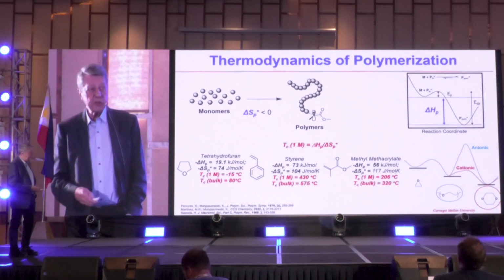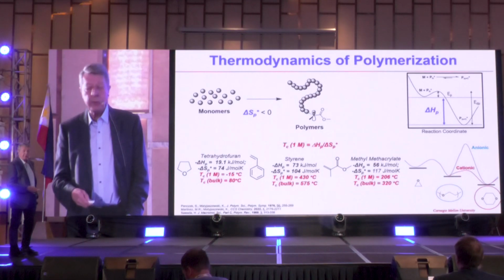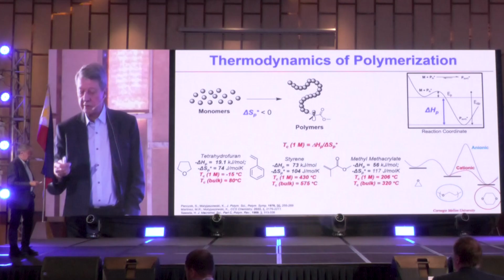So by selecting the right mechanism, we can prevent this 1,4-dioxane formation, using anionic rather than cationic polymerization. Or if we have ethylene here, this is polyethylene, the thermodynamic product is cyclohexane. We don't know how to, at room temperature, convert polyethylene to cyclohexane, but maybe some of you will develop it in the future, and it would dramatically change what happens with the polyolefin markets.